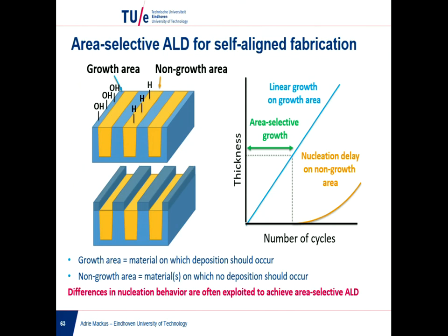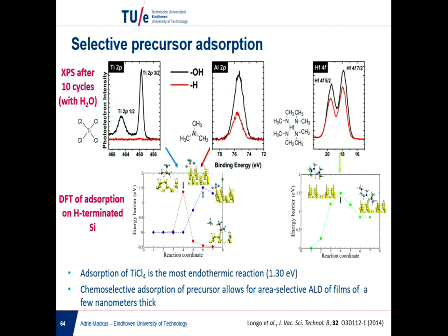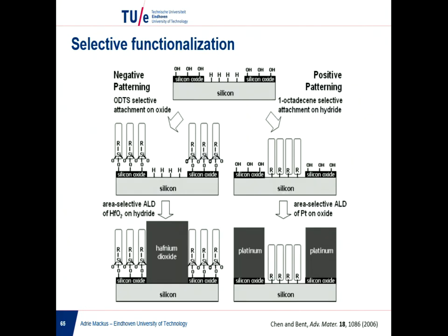If you think about an ALD chemistry, you typically understand the reaction mechanism, but there are always some side reactions that also play a role here. So in this case, some water may, for example, physisorb on the hydrogen terminated surface, and then you can get kind of a CVD type of reaction where the incoming precursor reacts with this physisorbed water, and in that way you can create a site for the nucleation to start.